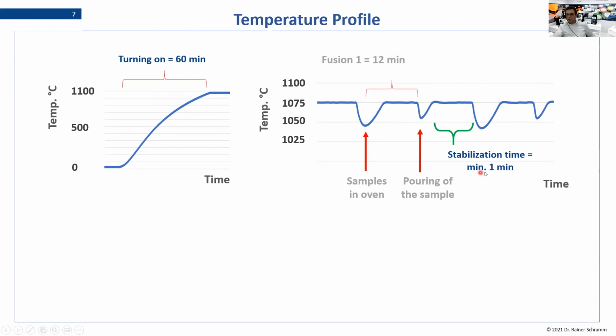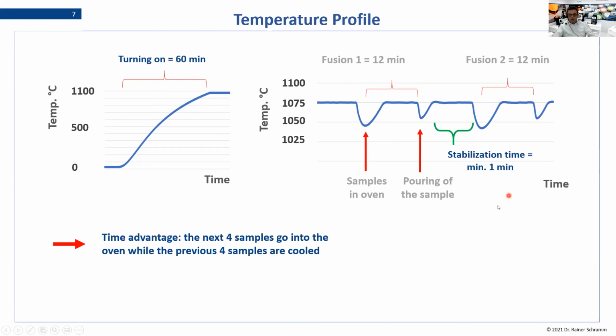It will be, for routine, 1 minute. And let me say, if you do chlorine or fluorine fusions, then it should probably be something around 3 minutes, to give a little bit more time to have exactly the same temperature conditions as before. So then you do your second fusion here. That means we have a time advantage here.